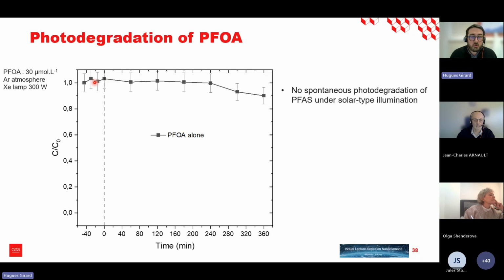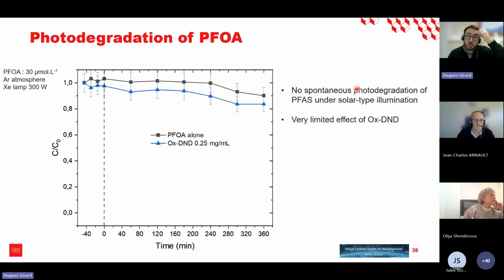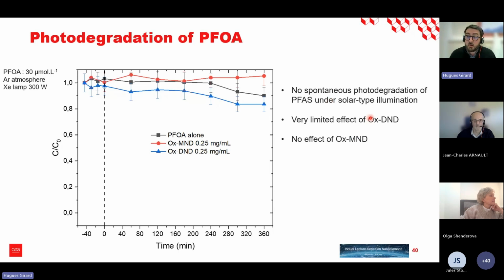When there is no photocatalyst, of course, nothing is happening because you cannot destroy or attack the PFOA with only light. But then if we add a little bit of oxidized detonation nanodiamond, you can see that we have a little bit of adsorption of PFOA at the surface of the detonation nanodiamonds, but then after there is no real photoreactivity with them, so a different behavior compared to the production of hydrogen. Then we also tested the oxidized milled nanodiamond. You can see here that this is even worse because we don't have any adsorption of PFOA at the surface of the oxidized milled nanodiamond, and then after no reactivity at all.